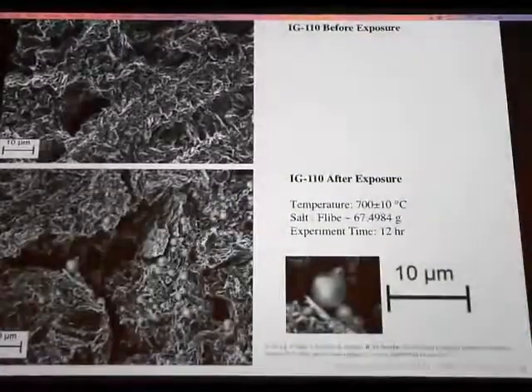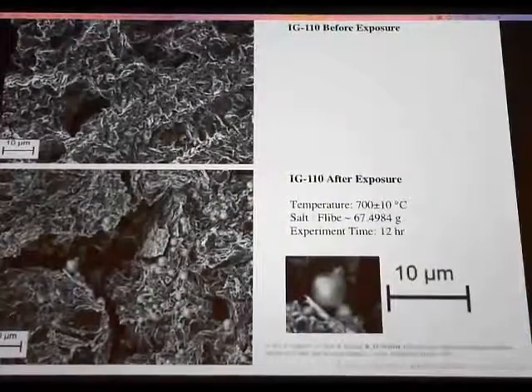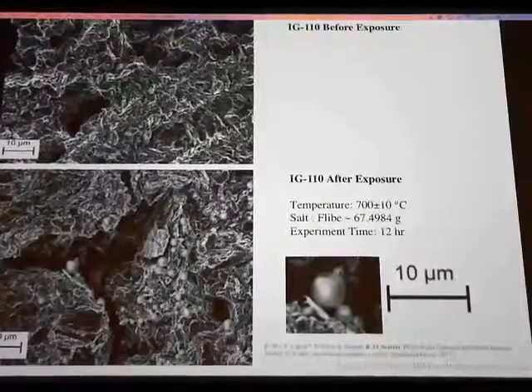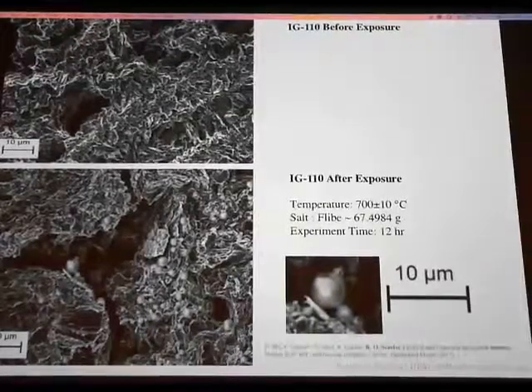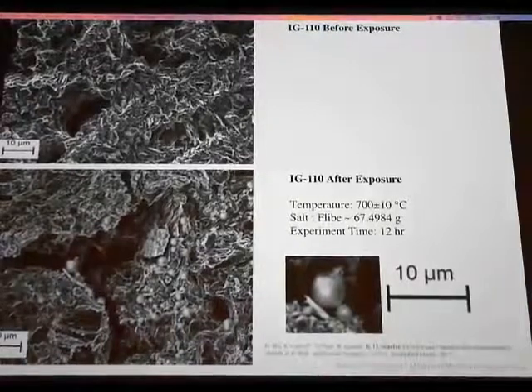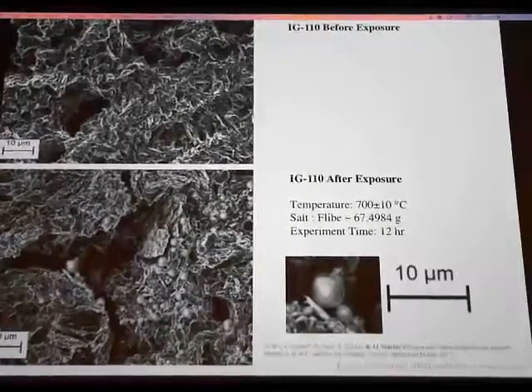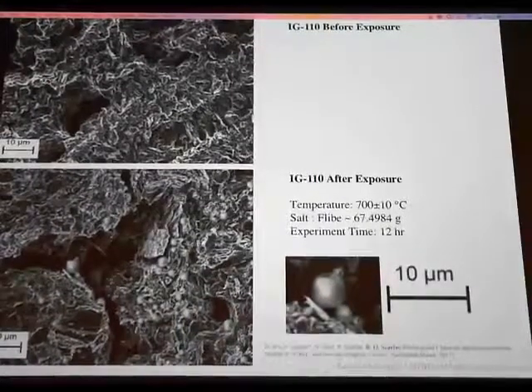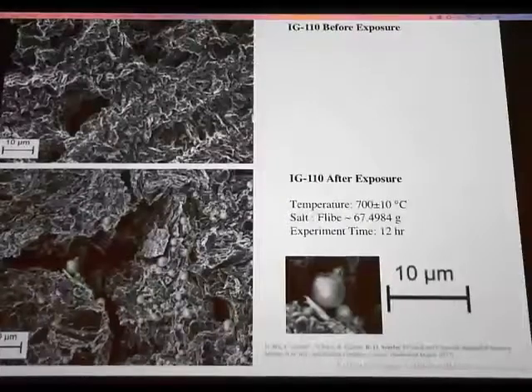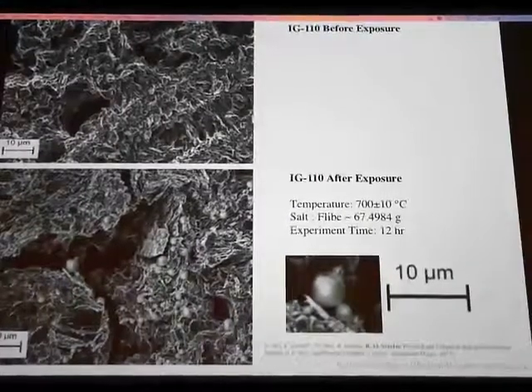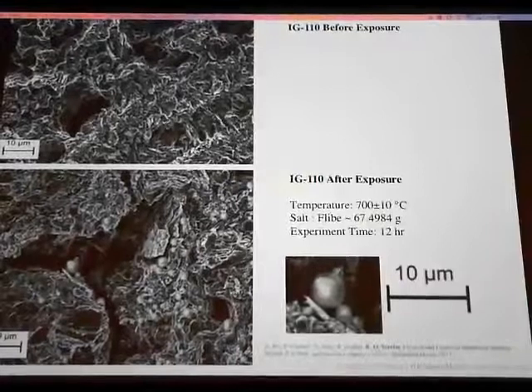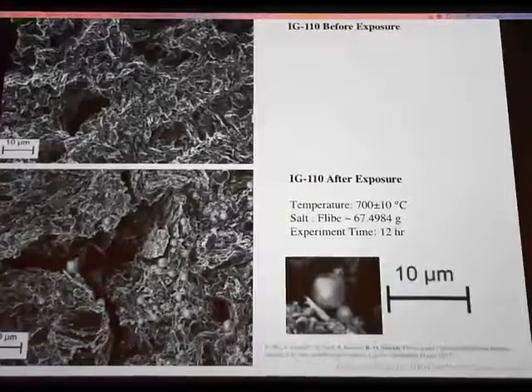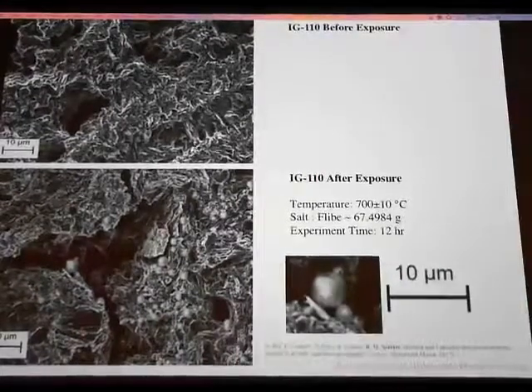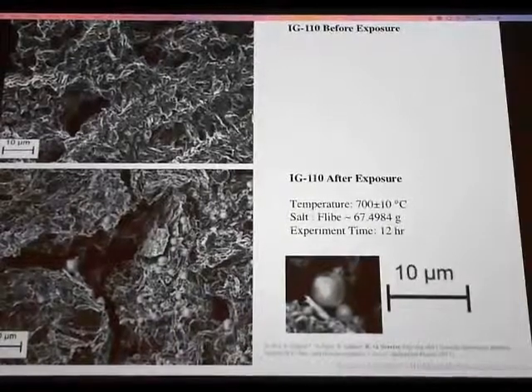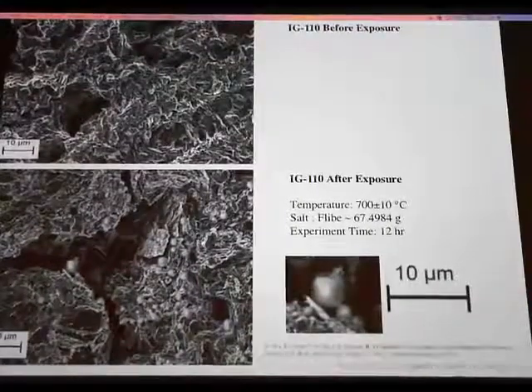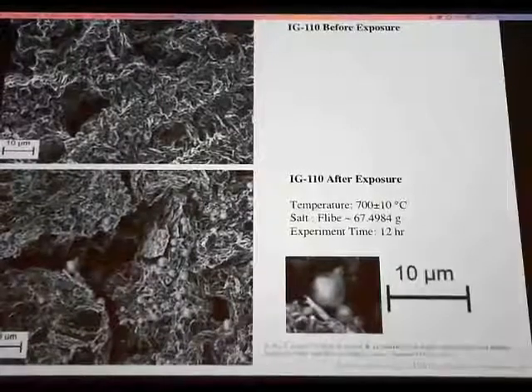So we want to understand if we were to take the hydrogen graphite data and the hydrogen salt data and put them together, would we get the right number for hydrogen from salt into graphite, or is there some sort of interface reaction that happens between the salt and the graphite that changes the tritium transport? And so we exposed nuclear graphite to flibe for 12 hours at 700 Celsius, and we observed these intriguing spheres. And we want to know what they are.